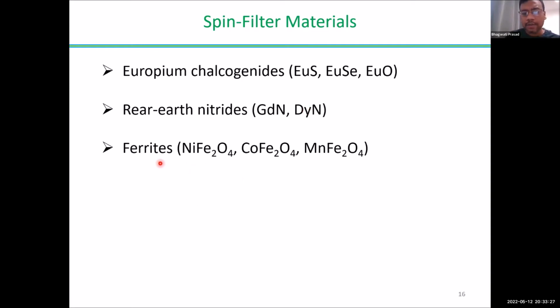The other set of materials, called ferrites, have a higher TC. People have grown them, but these materials have their own issue because they are spinel structures, and when you want to grow them on electrodes, which are typically perovskite systems, like when you want to grow oxide systems, at the interface you create some sort of defects, which reduce the spin polarization, especially when you want to see room temperature applications.